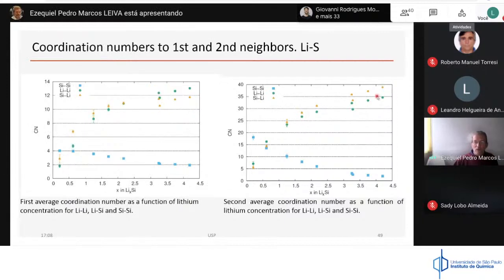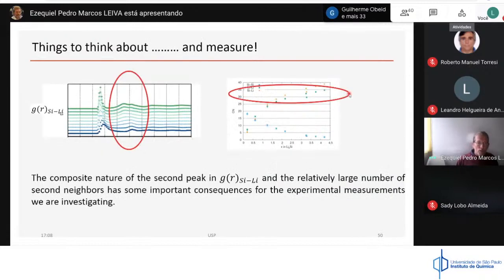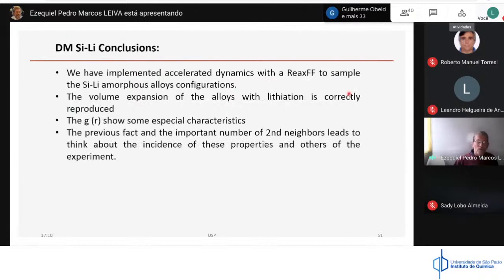You have a very important number of second neighbors in this system. Well, this is something we are considering now, and this is what I want to show you. These are very, very brand new results. So we have put to work a reactive force field where we can study the formation of lithium amorphous silicon alloys. We have reproduced the volume expansion, and the distribution function has shown some interesting characteristics which are being investigated now to know the consequence for some techniques.